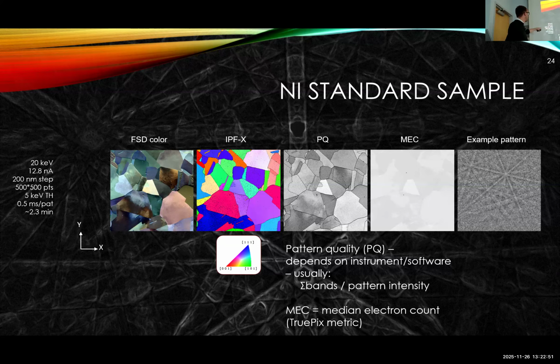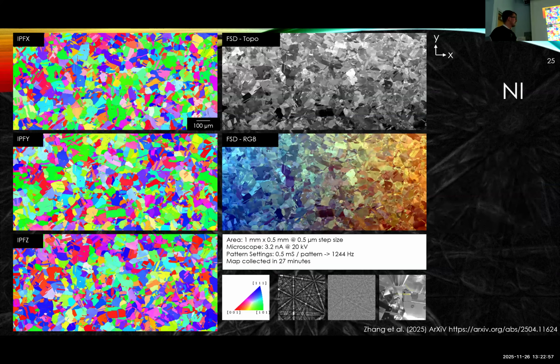This whole map is 500 by 500 points, and it was collected in 2.3 minutes for this data set. This is a slightly bigger map. So this is 1 millimeter by 0.5 millimeter, 500 nanometer step size. It was collected in this case at 1244 hertz, 27 minutes, and now shows us a huge number of grains from our nickel example sample as presented. We have the IPF, the colors of orientation, and then we have some FSD colors to give us microstructure and quality, and this is the setup that's presented there.